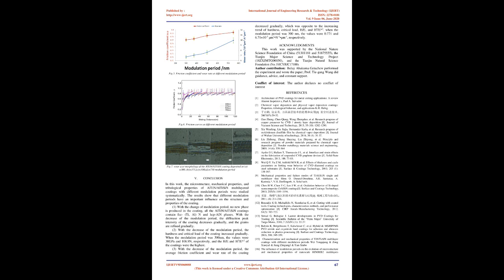D. Analysis of hardness and elastic modulus of AlTiN/AlTiSiN coating. Fig. 4 shows that with the decrease of the modulation period, the hardness of multilayers increased gradually. When the modulation period is 300 nm, the hardness is up to 30 GPa, and when the modulation period is 750 nm, the modulus of elasticity is up to 369.1 GPa. This is mainly due to the increase in the number of layers, the increase of the number of interlaminar interfaces, and the repeated nucleation between interfaces.